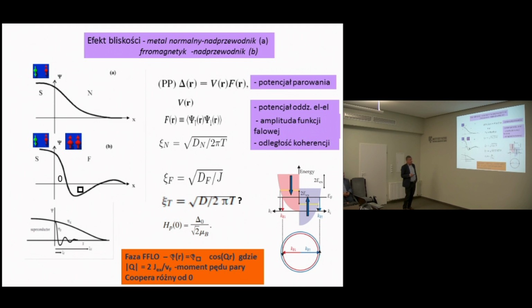However, if you have a moderate ferromagnet, then due to the Zeeman effect there will be splitting of levels, and in such a case, Fulde, Ferrell, and Larkin, Ovchinnikov showed that the order parameter does not decrease monotonically, but is oscillating, damped oscillating, and such a phenomenon is very short range, up to 1 nanometer. And in such a case, the momentum is non-zero.